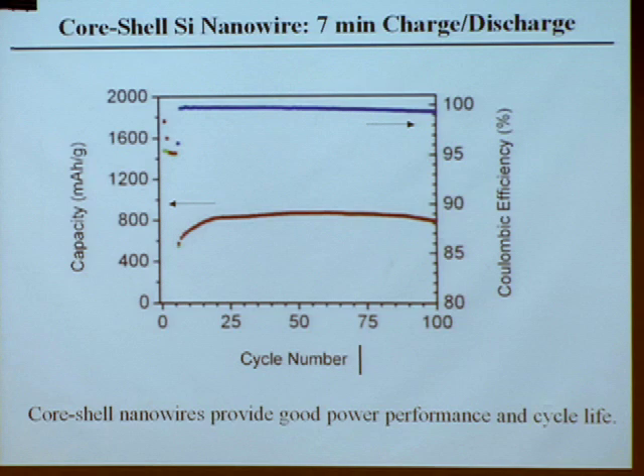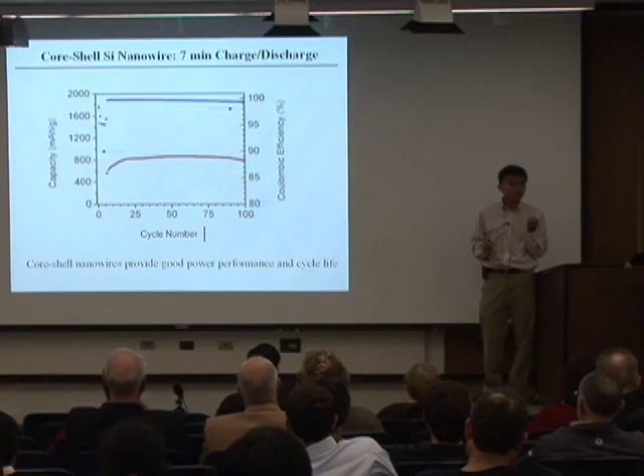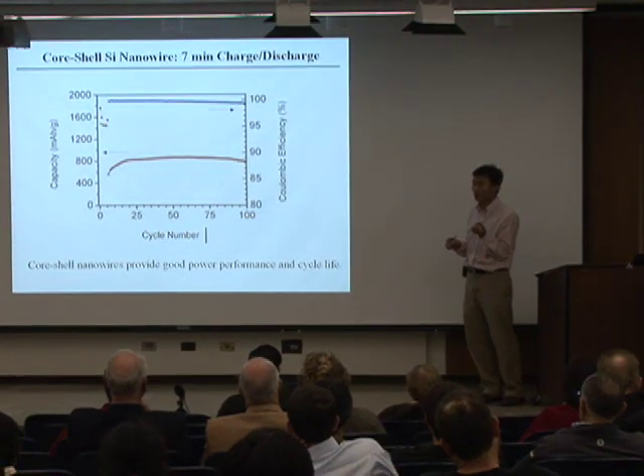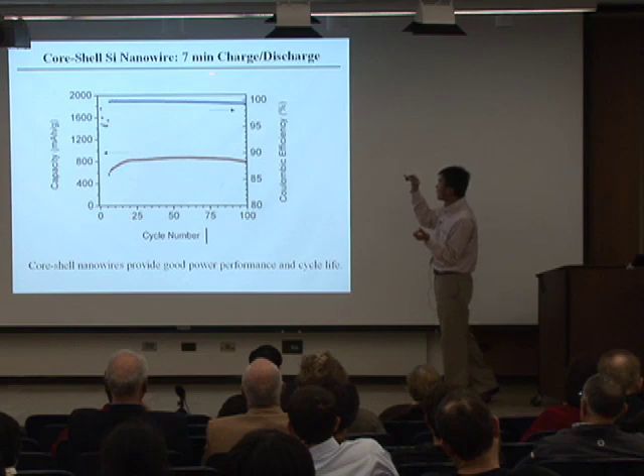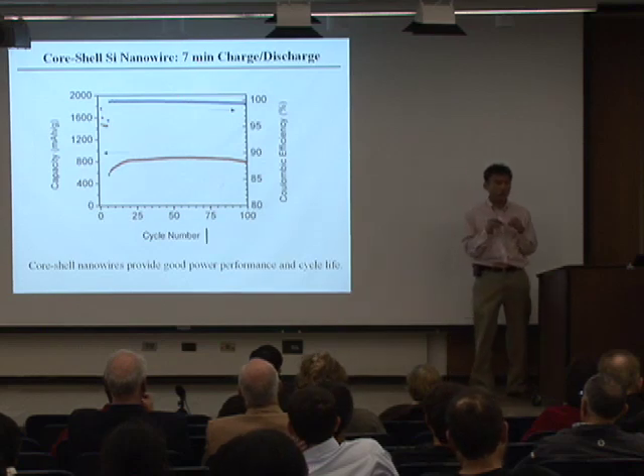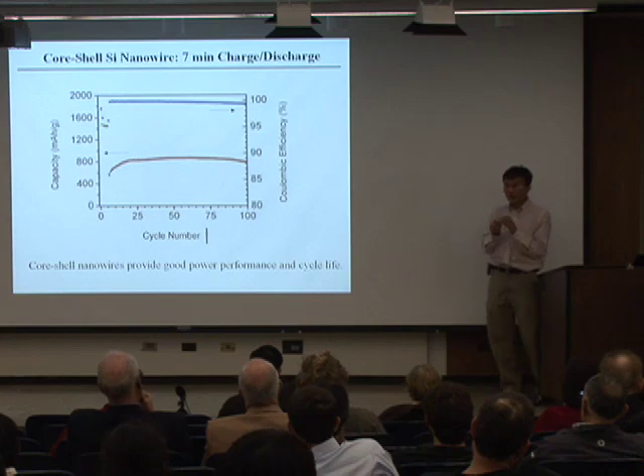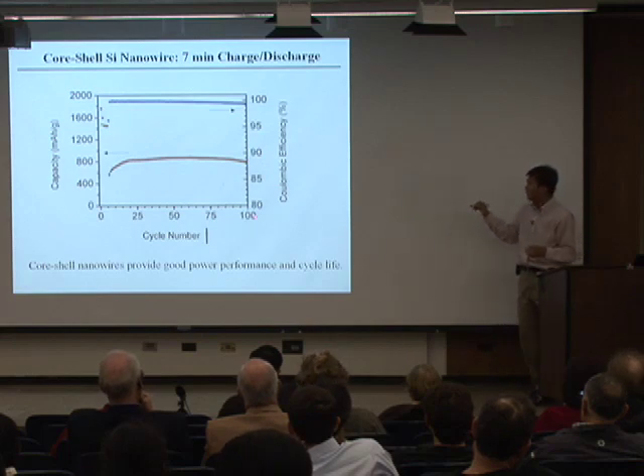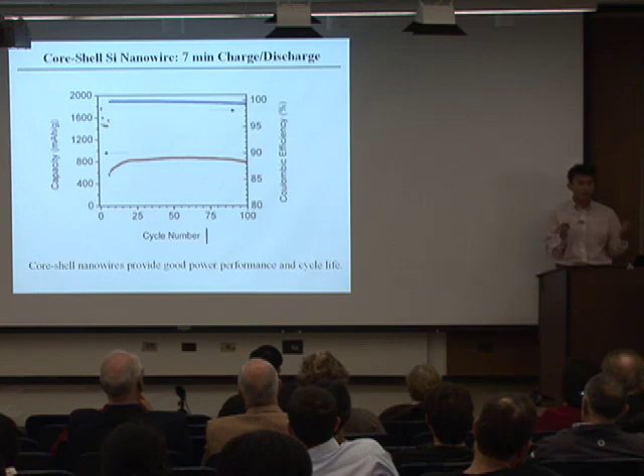Since we limited our potential for charging, we are not going to reach, say, 3,000 or 4,000 milliamp hours per gram of capacity. That's very high. We perhaps only reach close to 1,000, but that's good enough. This is 3 times that of carbon. That's very high. What you gain is an extremely fast charging and discharging rate, and also your lifetime becomes extremely long. Within 100 cycles, you really don't see any decay.